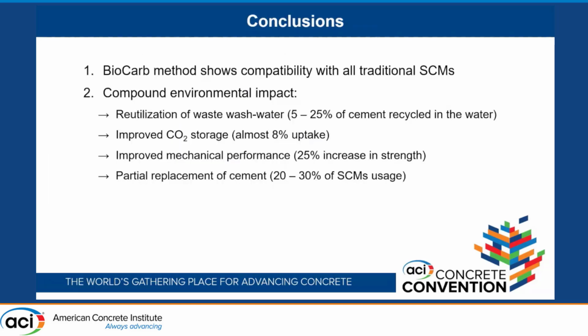So to wrap it up, this BioCarb method shows good compatibility with all the SCMs in the study. And then we have the compound environmental impact that we're looking to achieve those goals. So we have the reutilization of wastewater, which could vary between 5 and 25% of cement present in the slurry, as well as the improved CO2 storage. We're almost at 8% uptake, as well as the improved mechanical performance. We saw a 25% increase in strength, and the partial replacement of cement up to 30%.